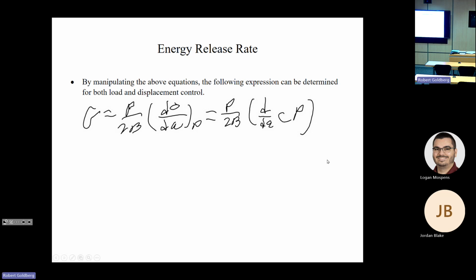Compliance by the load, and we can pull once again the load out. So we have that the strain energy release rate is equal to P squared over 2B times the derivative of the compliance with respect to the crack length. And if you go through a similar argument, you get the same equation for the case of displacement control. So it's just plugging in the definition and still using what's constant. And obviously what you do for the second case, you would say that the displacement is equal to the compliance times the load. You pull things out, or do the derivatives, and you get that same idea.